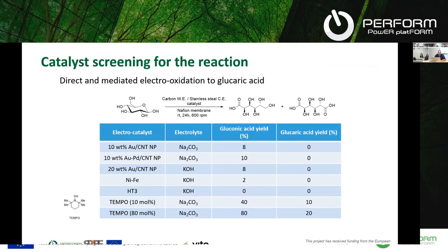So where we started was with a catalyst screening for this reaction, so for the glucose to glucaric. First, of course, is the mixture of gluconic and glucaric acid. And there were several electrocatalysts prepared by partner INSTM based on gold, palladium, and all these were deposited onto carbon nanotubes as nanoparticles. But for most cases, I'm summarizing this now, we saw very little to no yield of glucaric acid and only small amounts of gluconic acid formed. On the other hand, when we tried using the tempo-mediated approach in bicarbonate or in carbonate solution, we found at least some yields to glucaric acid and a lot to gluconic actually.